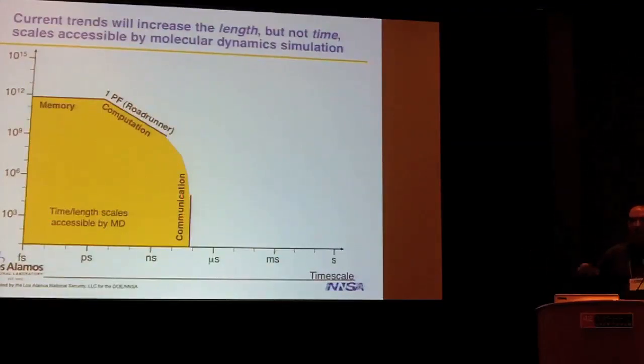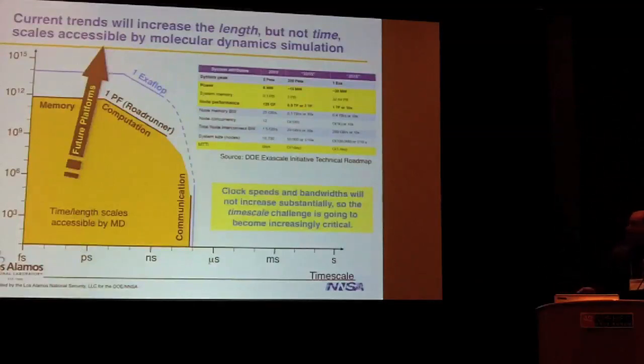So of course this wall depends very strongly on the network, the interconnect, and it will vary from system to system, but ballpark, it's somewhere approaching a microsecond, somewhat less. As we go forward with the projections towards exascale, by definition, the floating point performance is going up 3 orders of magnitude. The projections from power and cost and constraints, and also some pushback from the application community, is that the memory capacity may go up 2 orders of magnitude. But the communication, and particularly the ratio of the communication to the flops, isn't going up much, if at all. So this limit is barely shifting at all. So as we go forward, this linear scaling region is getting farther.